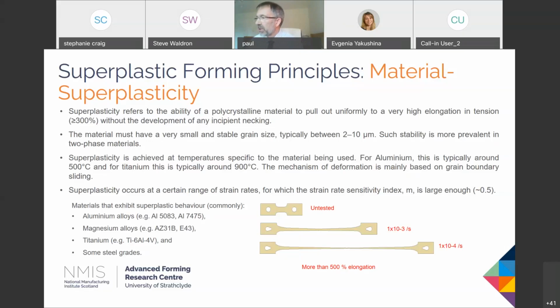Now, to jump back to my definition, I said that superplasticity is not a property that all materials demonstrate, and you see a list on the bottom left there of some of the alloys that are commonly superplastically formed. Really the main ones are the aluminium alloys, and you see a couple listed there. 5083 classically is a very classical superplastic material. And in the case of titanium, which is the other main material that tends to be formed by a superplastic forming process, Ti64 is the most widely used alloy.